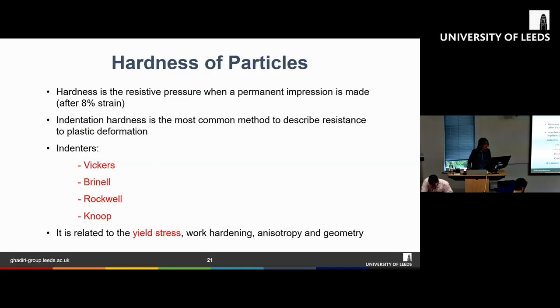So how do we measure hardness, and what is hardness? Hardness, like I mentioned before, is the resistive pressure when a permanent impression is made, and this is typically after 8% of strain. Indentation hardness is probably one of the most common methods used to measure the resistance to plastic deformation. Some of the most common indenters are Vickers, Brinell, Rockwell, and Knoop indenters. Hardness measurement is related to yield stress, work hardening, anisotropy, and geometry.